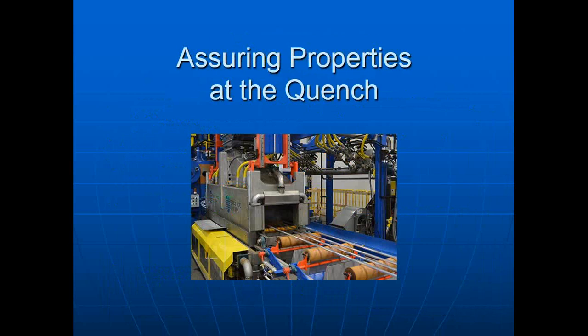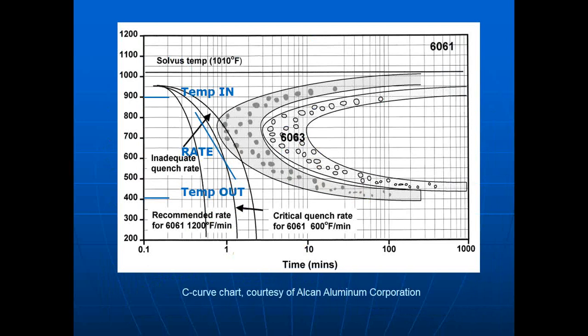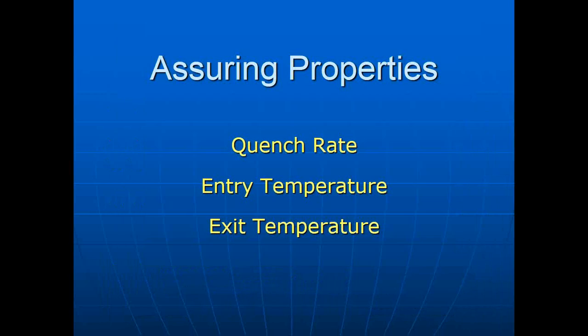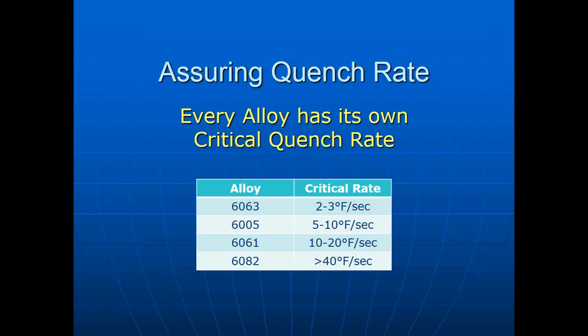So how do we assure properties at the press quench? The three properties we talked about before: temp in, rate, and temp out. Quench rate, entry temperature, exit temperature. Every alloy has a critical quench rate. Here we see a list. 6061 is probably the most common structural alloy, although automotive is using a lot of 6082 now. And we see 20 degrees a second, even 40 degrees a second. Each alloy has its own requirements.